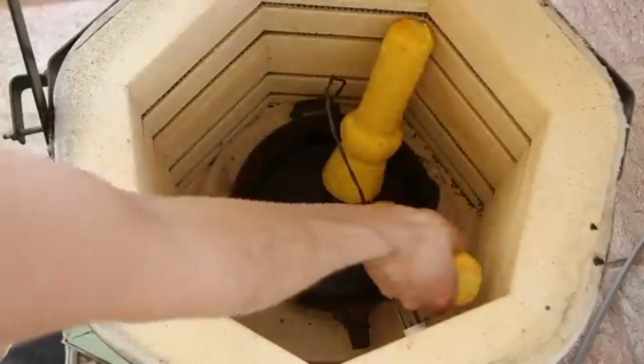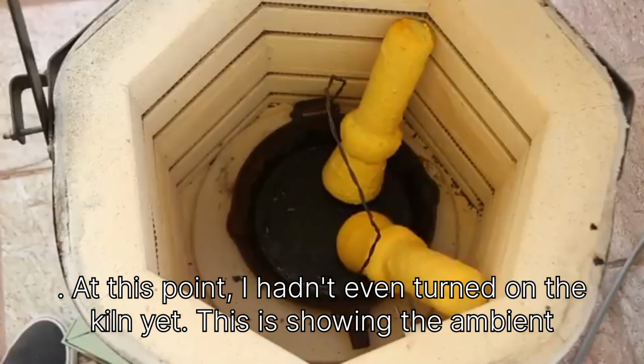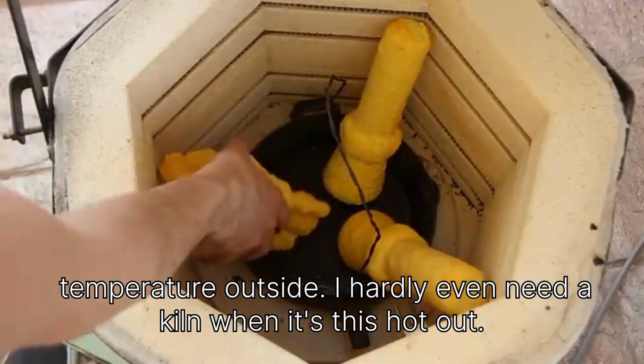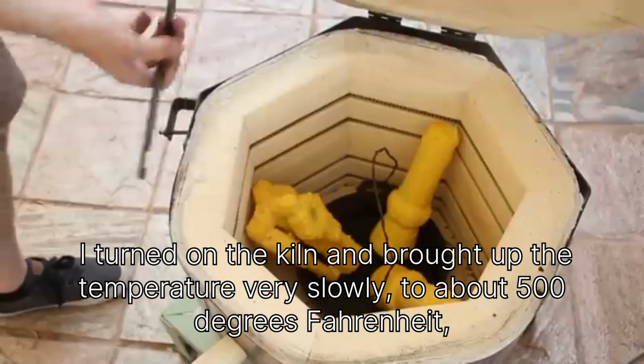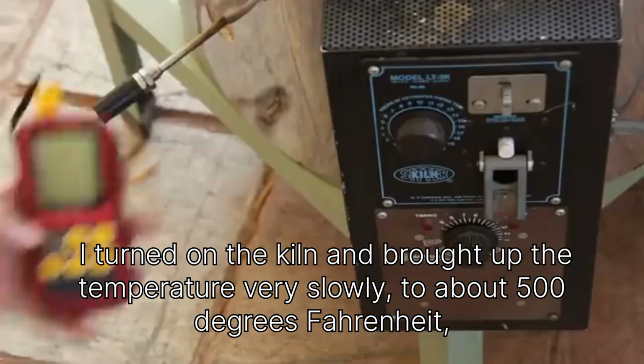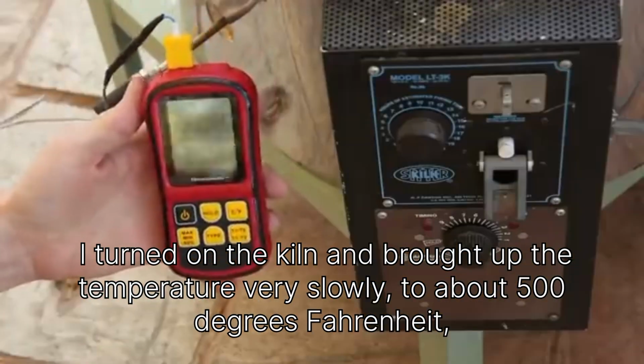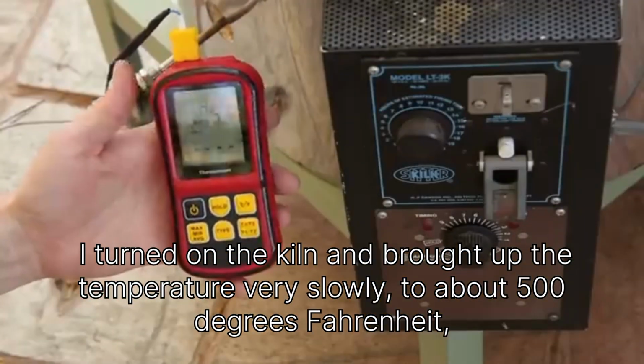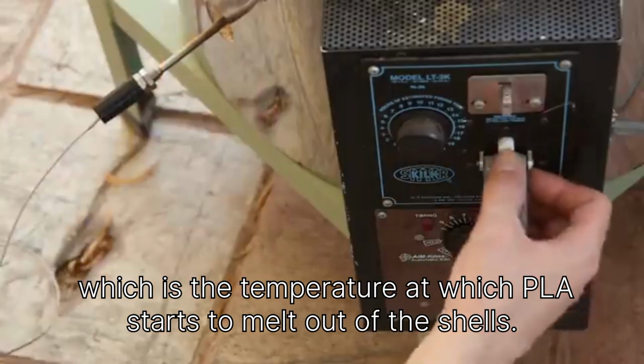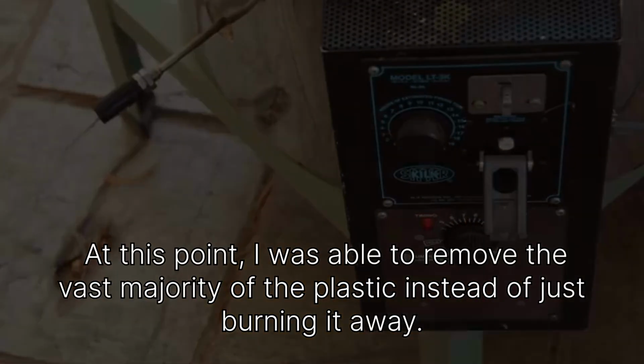At this point, I hadn't even turned on the kiln yet. This is showing the ambient temperature outside. I hardly even need a kiln when it's this hot out. I turned on the kiln and brought up the temperature very slowly, to about 500 degrees Fahrenheit, which is the temperature at which PLA starts to melt out of the shells.